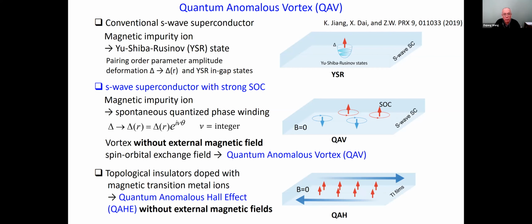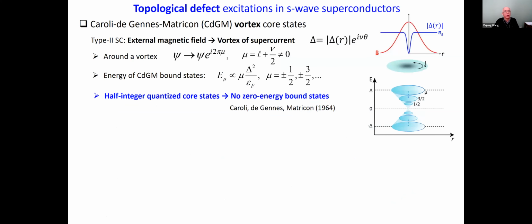So let me begin immediately with what is a vortex excitation in a type 2 superconductor and what are vortex core states. And here I have a vortex which is a deformation of the amplitude to 0 of the pairing field, and then a quantized phase winding around it, so that I have a circulating supercurrent around the vortex. And in the vortex, I have the vortex core states.